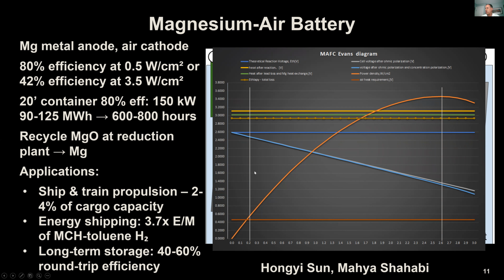Starting at just 0.2 amps per square centimeter, it produces 0.5 watts per square centimeter at 80% efficiency. Or you can run at 7 times that power density at 2.6 amps per square centimeter. That's 3.5 watts per square centimeter, but at just 42% efficiency. So it has this wide range of operating conditions. Based on this, a 20-foot shipping container with a stack of 10 cells delivers up to 125 megawatt hours at 150 kilowatts for 600 to 800 hours of operation, enough to get a ship across the Pacific.